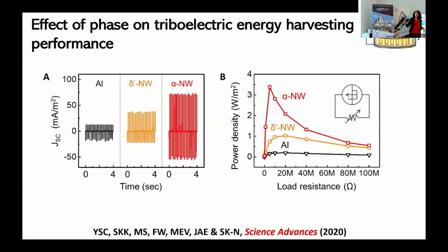So this only manifests in these nanostructured samples of nylon, and they're very thermally stable. You can heat this material, bring it back down, and nothing changes. It's still able to hold on to that polarization.